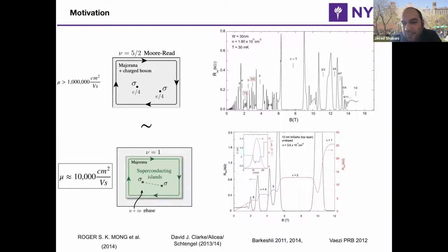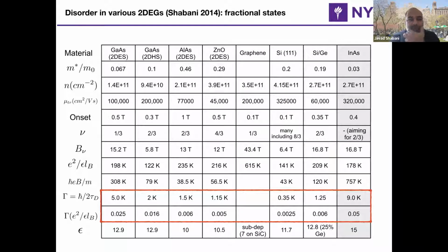So in the last 5-6 years, I've worked on indium arsenide quantum wells, and indeed, they are not as good as other materials. So let me show you a quick review I did in 2014 on various materials that have shown fractional quantum Hall effect. If you just focus on the disorder parameter or Landau level broadening, most of these materials have already shown some sort of a fractional state. But indium arsenide hasn't. And the question we were asking is whether this is disorder related or not. If you compare the disorders, they're not really off. It's 0.05 versus 0.025, where the first gallium arsenide 1/3 was observed. It's just a factor of 2.